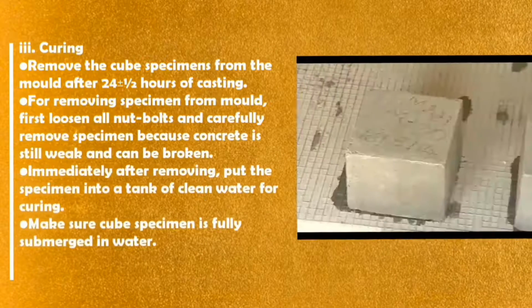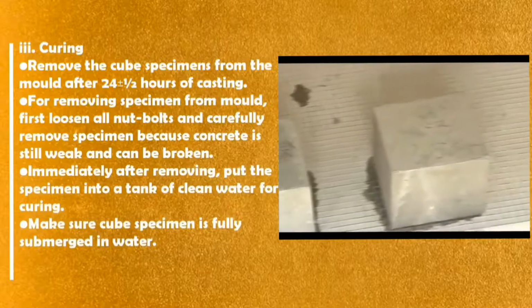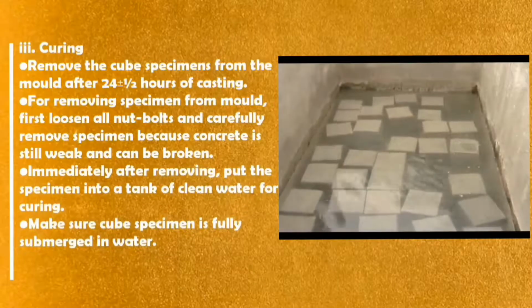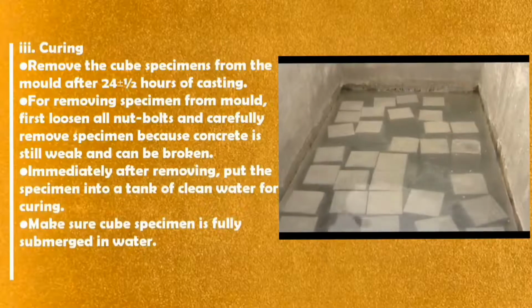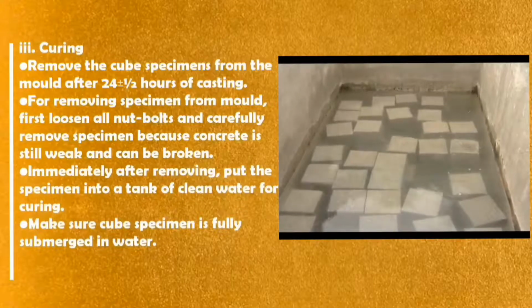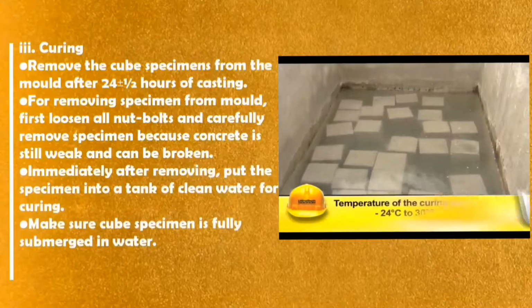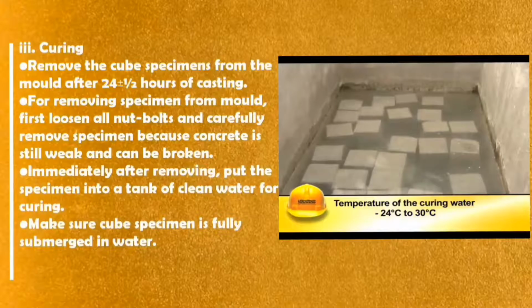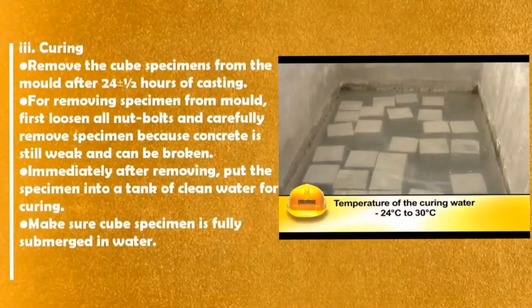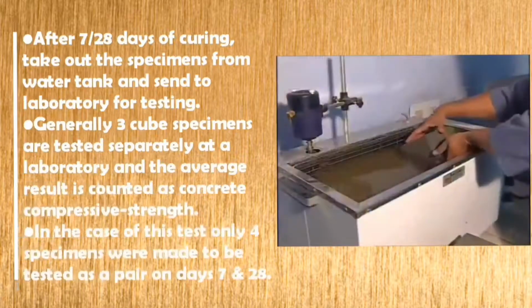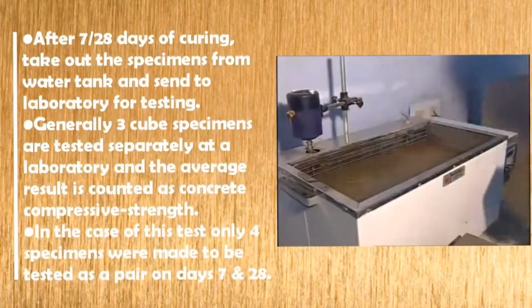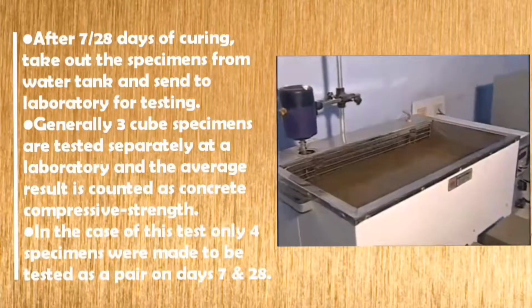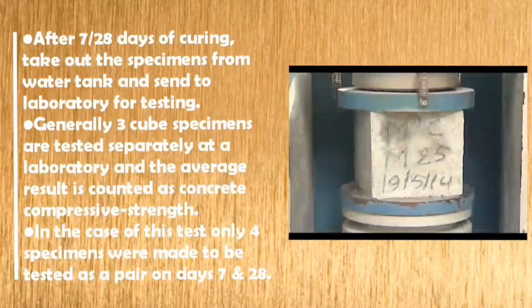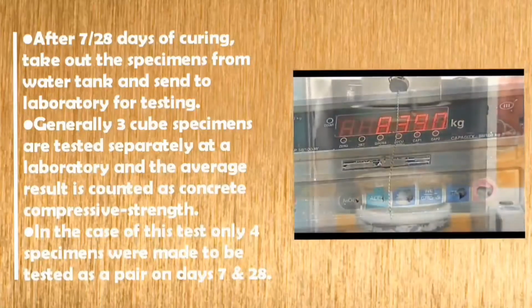Lastly, curing. Remove the cube specimen from the mold after 24 hours of casting. For removing the specimen from the mold, first loosen all nuts and bolts, and carefully remove the specimen because concrete is still weak and can be broken. Immediately after removing, put the specimen into a tank of clean water for curing. Make sure the cube specimen is fully submerged in water. After 7 and 28 days of curing, take out the specimen from the water tank and send it to the laboratory for testing. Generally, 3 cube specimens are tested separately at a laboratory and the average result is counted as the concrete compressive strength.